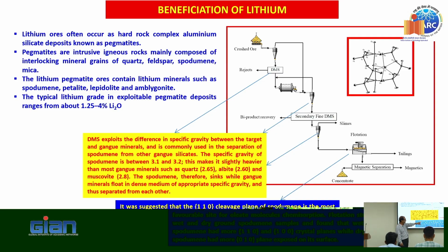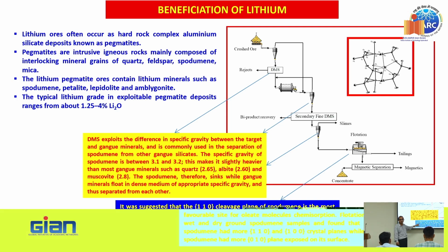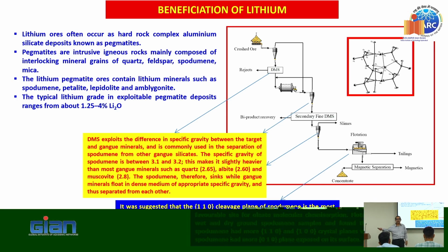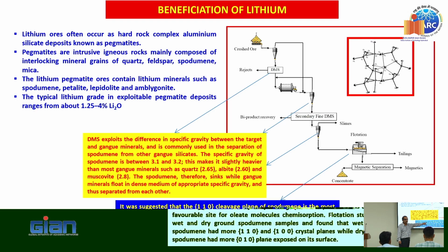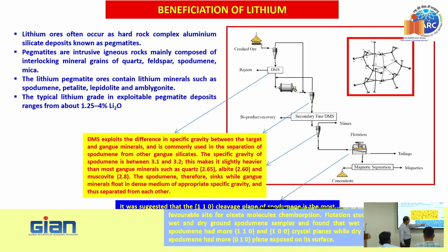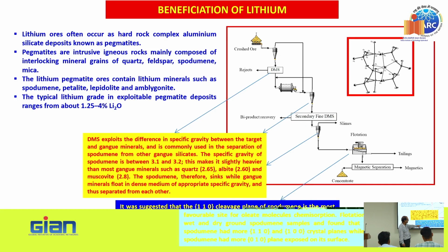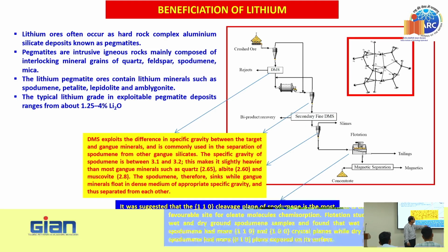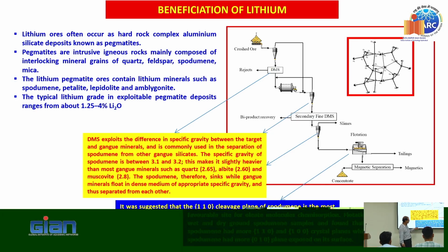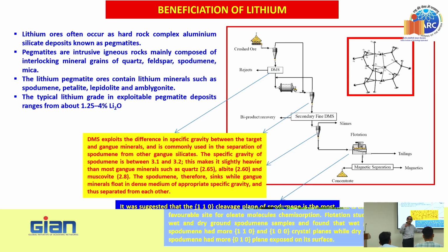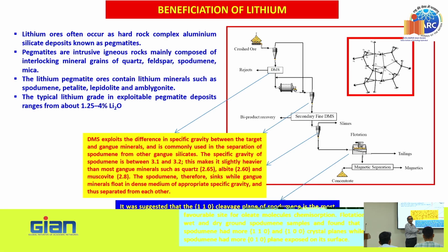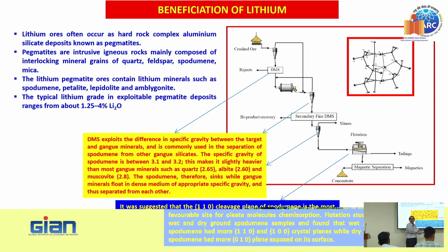It is suggested that the 110 cleavage plane of spodumene is the most favorable site for oleate. As I was telling you in that molecular architecture discussion, this is the most favorable site for adsorption of oleate on spodumene. And the chemisorption takes place. Flotation studies on wet and dry ground spodumene samples found that wet ground spodumene has more of 110 and 100 crystal planes, while dry ground one has got 010. That is why we always have to do wet grinding, because only then you will have the adsorption of oleate on that particular plane. That is the most favorable cleavage plane.